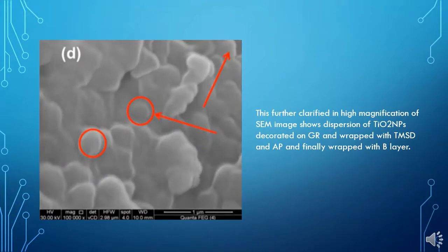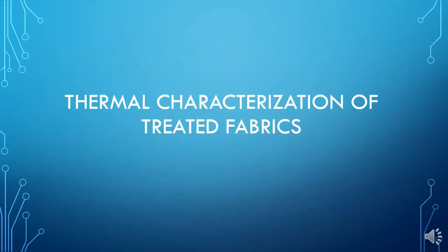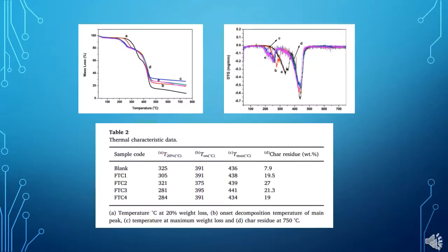While this next image shows that further clarified in high magnification of the SEM image of the FTC4, which shows the dispersion of the TiO2 nanoparticles decorated on graphite and wrapped with TMSD and AP, and finally wrapped with the binder layer. Next, we will talk about the thermal characterization of treated fabrics.